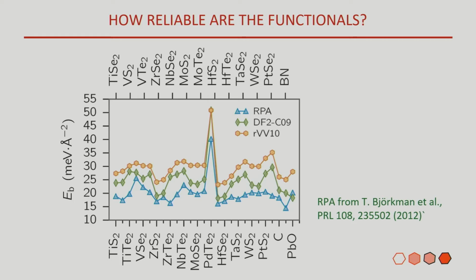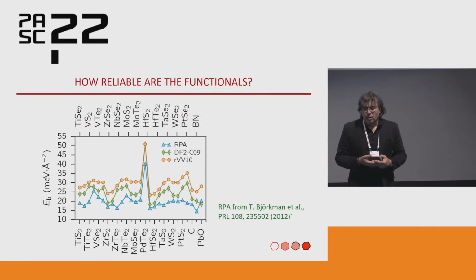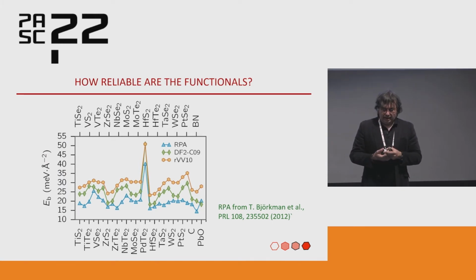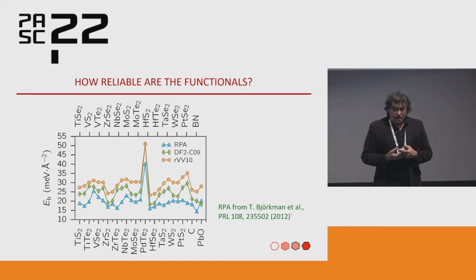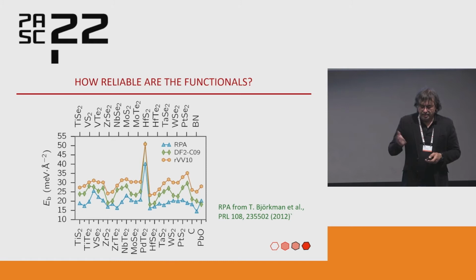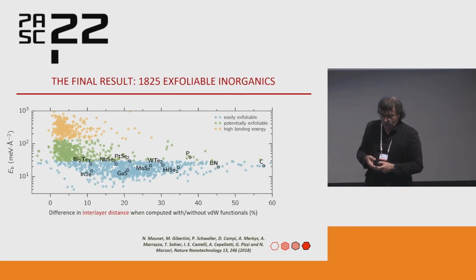Just to make sure that the physics is good, the quantum mechanics is good, since the most important quantity that we want to calculate is the binding energy of the layer, what we had were very high-quality reference calculations done with something that is called the adiabatic connection in the random phase approximation from Björkman and collaborators. These are the blue data. These are the binding energies for around 25 materials. And when you use van der Waals density functional theory, in green and orange, I would say you have a very good agreement. It's not perfect, but it's also incredibly less expensive. And if anything, it overestimates the binding energy. So in reality, the materials would have even lower binding energies than what we calculate.